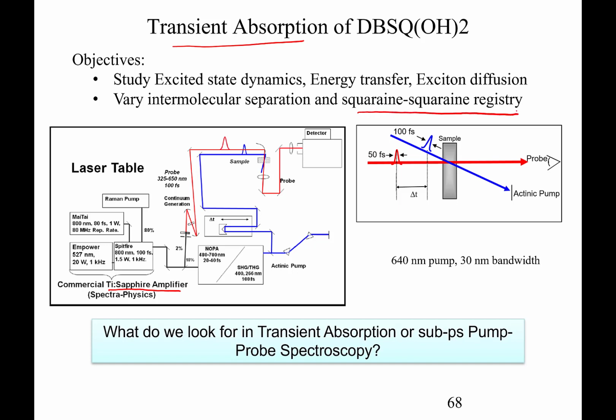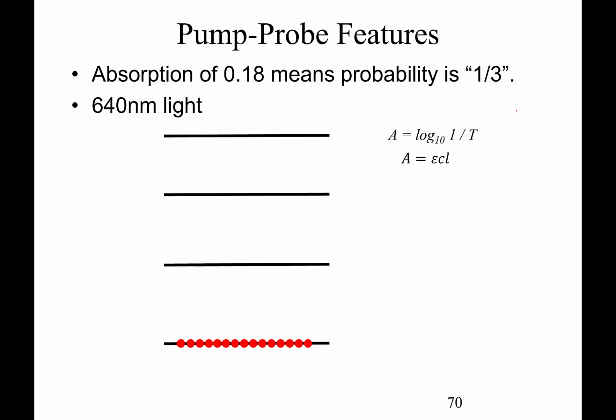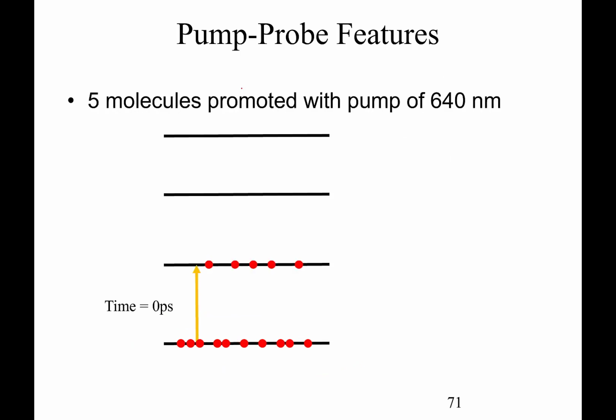So what do we look for in transient absorption or sub-picosecond pump probe spectroscopy? How it works, so what we have here is a ground state. We've got all our molecules sitting in the ground state, and we have a sample that's got an absorption of about 0.18, and that means that the probability of getting excited is about a third. So maybe we'll imagine we come in with 640 nanometers light, and we can take 5 of those 15 molecules, and we take those 5 molecules and we pop them up into an excited state with this pump of 640 nanometers.